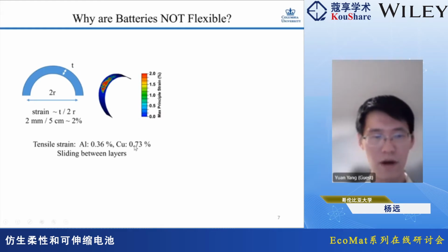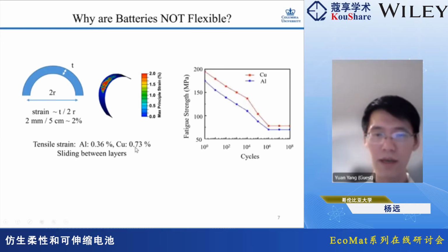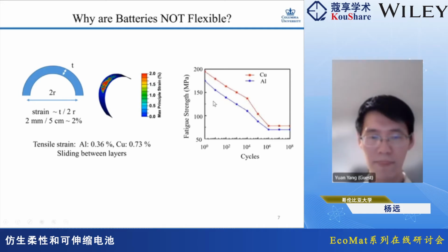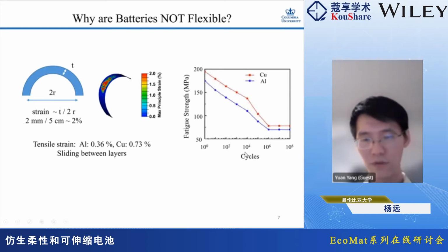The bending will also cause sliding between different layers, and such sliding-induced shear strains are also not good for the materials. And more importantly, the tensile strain and stress of materials will also decrease upon many cycles of bending. From this plot, you can see that when the cycles reach about 10,000 or 100,000, which is actually desired for flexible devices, the fatigue stress will be only about half of that at just one time of bending.